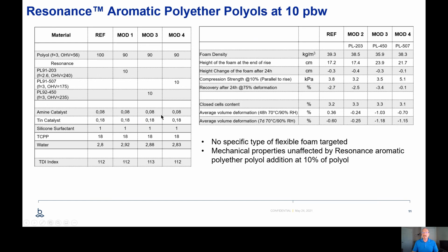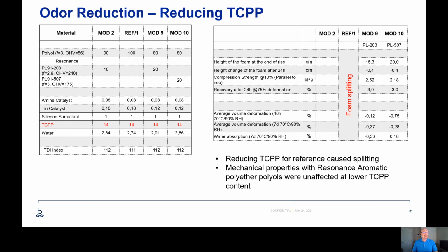You can see the closed cell content is about the same, very low. The foam characteristics that were prepared are very similar with respect to each other. Compressive strength, recovery after 24 hours, all those properties were not negatively affected at 10 parts of material. Same thing with some of the materials, we actually introduced 20 parts, and we can see that, again, the properties are unaffected. We also began to reduce the TCPP.